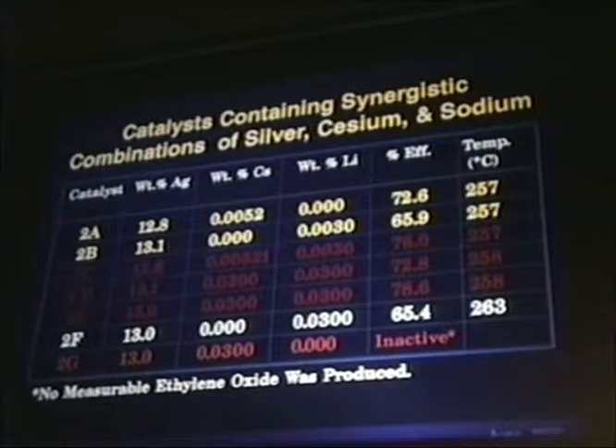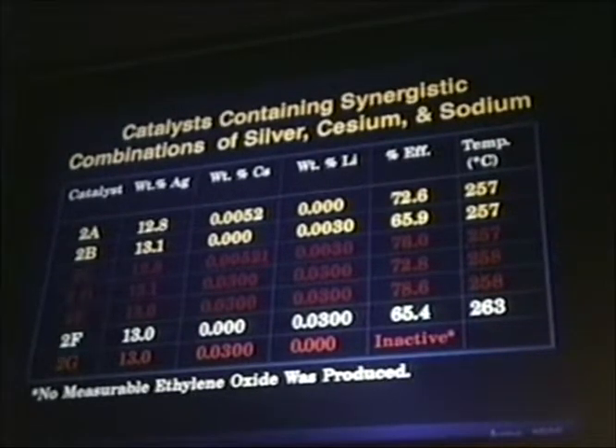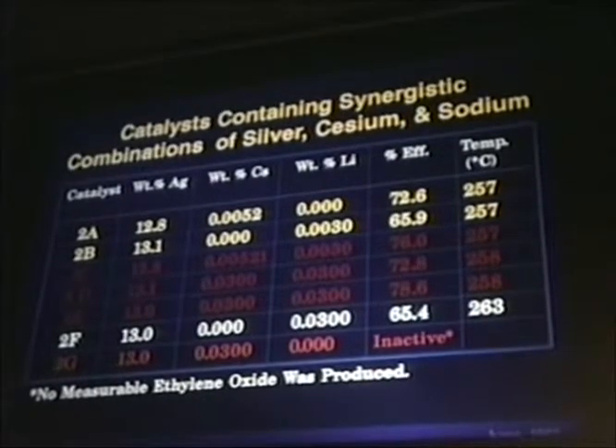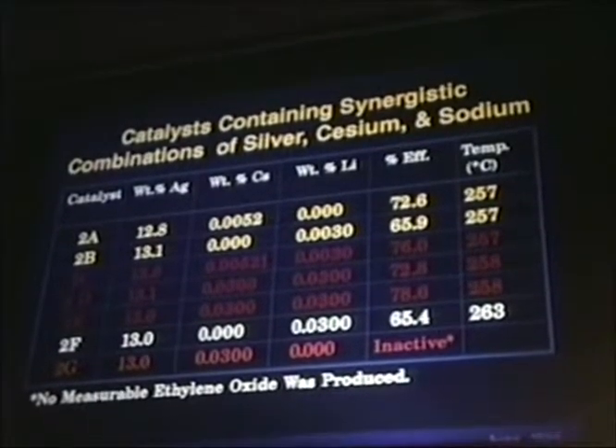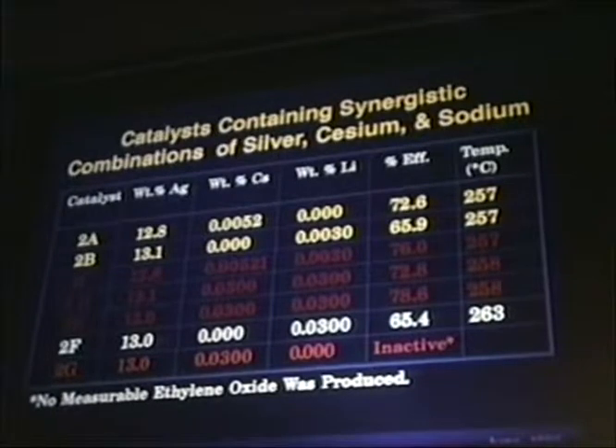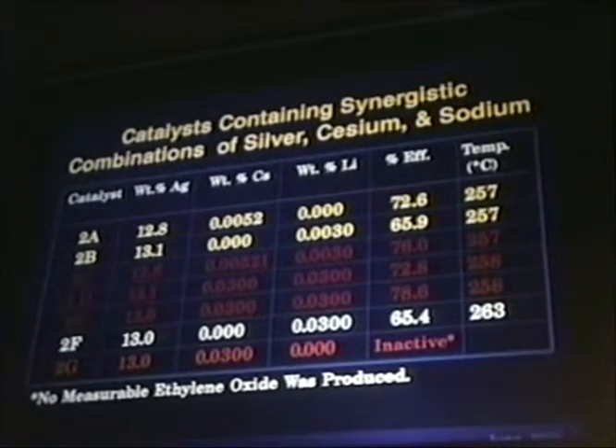So you'll see from this data that lithium, though by itself not a desirable promoter, when added to a cesium-containing catalyst, which is dead, makes it perform as well as some of the best catalysts in the mixed alkali system. Next slide.